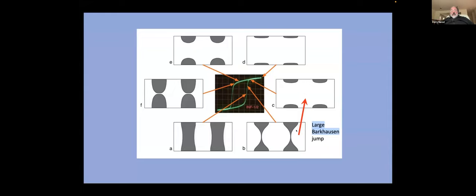And it's proportional to the energy available in that jump. And the energy is localized in the surfaces of the domain walls. And so the more surface area you have being reconnected from B to C, the more noise you're going to get. And it's not just inside the domains themselves that the surface matters. It matters on the surface of the foil over here, because they're actually tied together by physical principles.